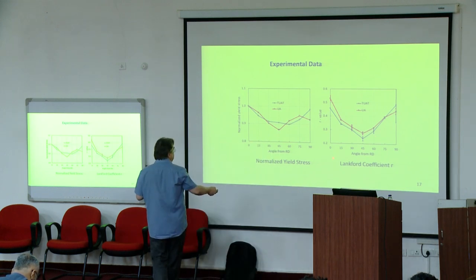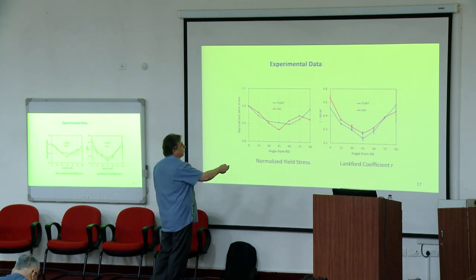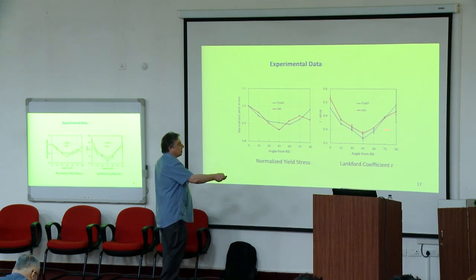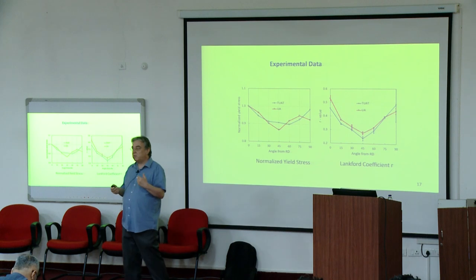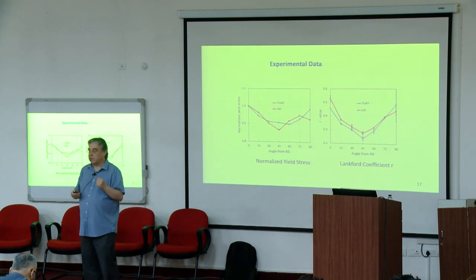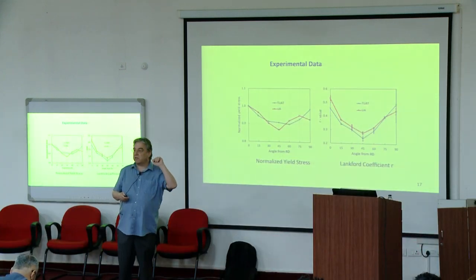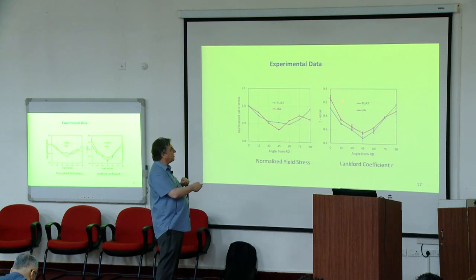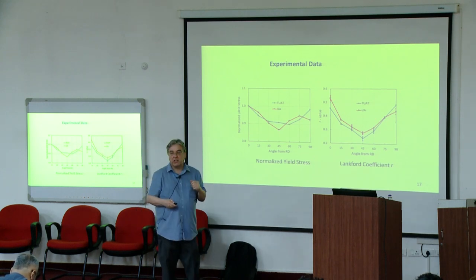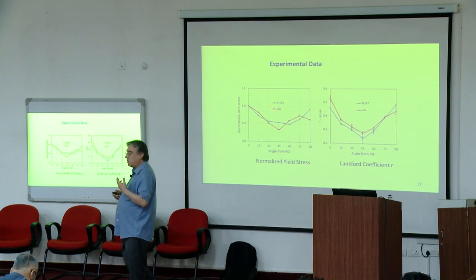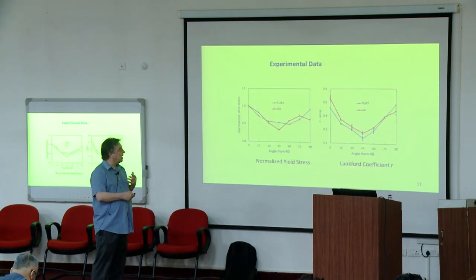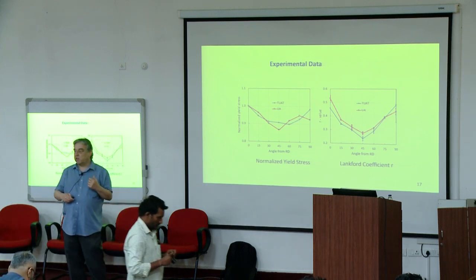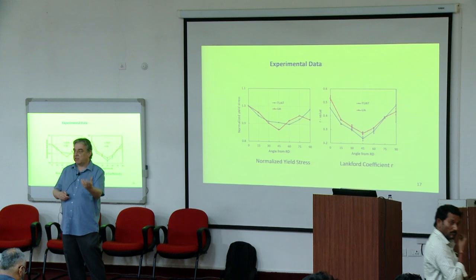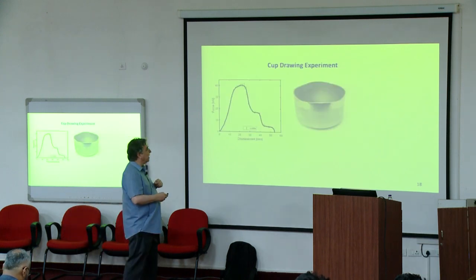And also you can see that they are anisotropic. So if you do the tensile test along the rolling direction, you have about 0.5. But if you do it along the diagonal direction, it's less than 0.3. So this means that the material behaves highly anisotropic. And it's, in fact, this phenomenon that is responsible for this earing behavior. So the larger the differences between the maximum and the minimum, the more earing that you will have. So actually, what we are trying to achieve here is to have a good prediction of this R value anisotropy, because this allows you to predict the earing behavior of the cup.